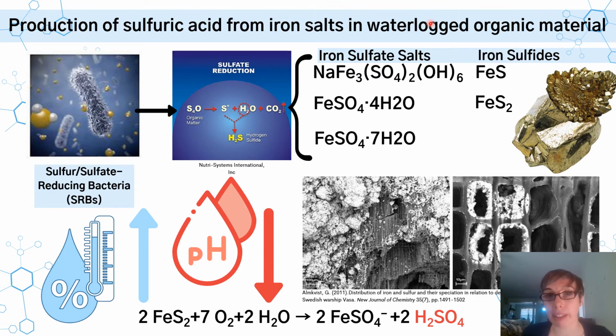That doesn't seem like a big deal on the surface, except that wooden artifacts are rarely alone in the burial environment and are often part of composite artifacts with metals or in otherwise some degree of contact with metals or their corrosion products, such as concreted materials that come from the ocean, which are often contaminated with iron or other metals as a result. The ensuing problem is that all these iron-sulfur combinations are susceptible to being solvated by atmospheric moisture or oxidative decay in the case of pyrite, and basically break down and turn into sulfuric acid, which tends to attack and deteriorate all components of the artifact, whether they are organic or inorganic.